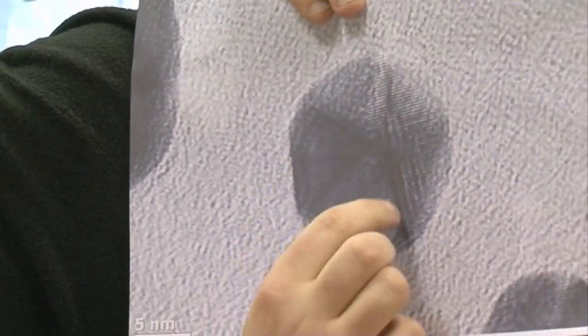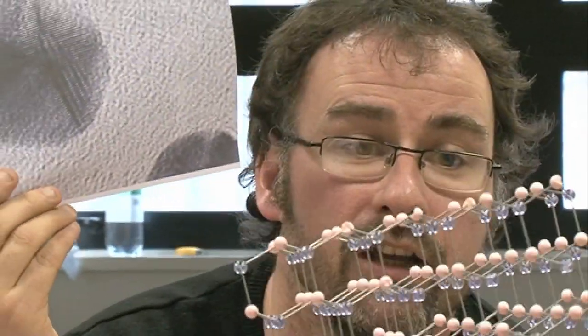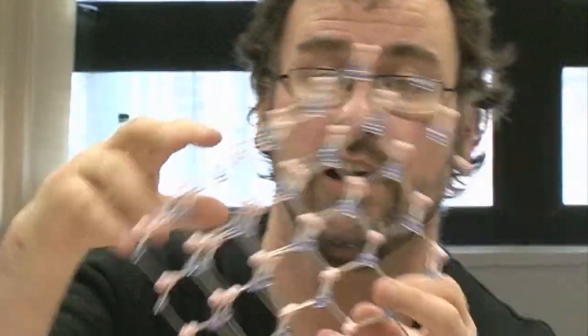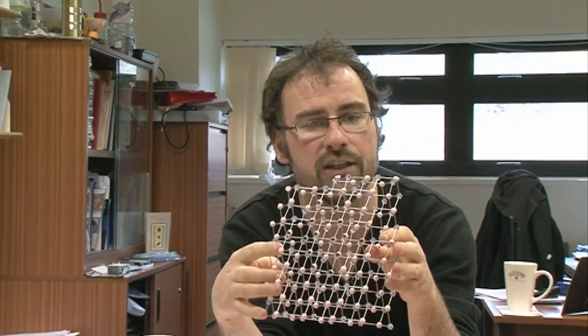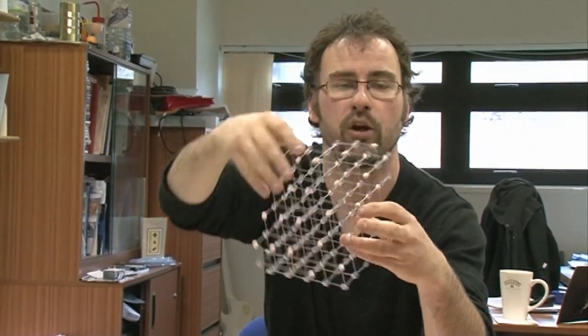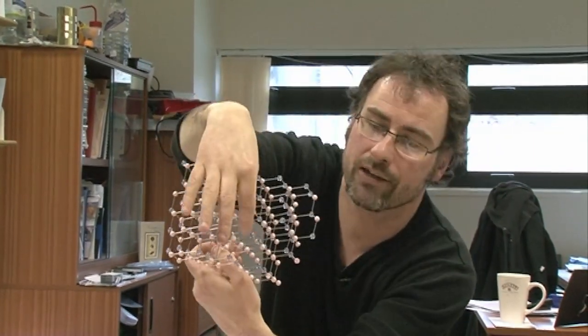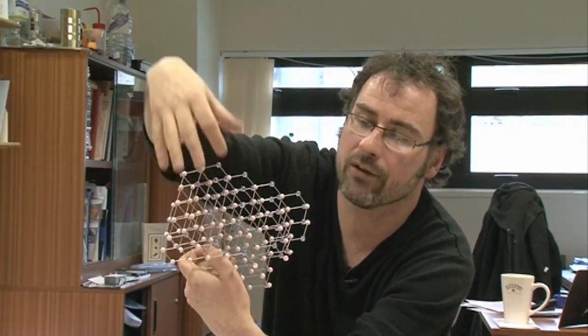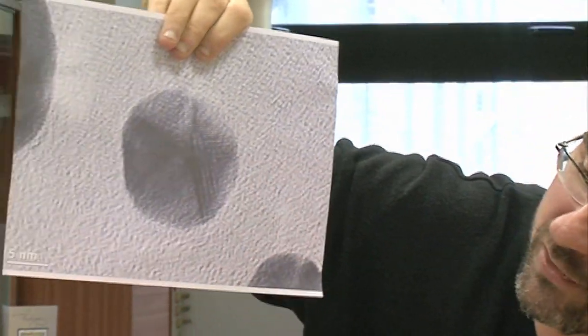You can sort of see these ridges, these edges, and those arise because when you form these particles, they grow out to a certain size and they have certain faces. It's not quite the same crystal structure, but it doesn't really matter, as gold has. And you have different faces, and those faces will have different reactivities, because if we look at different atoms on these faces, sometimes they're bonded to three atoms below, sometimes to two atoms below. That leaves what are called dangling bonds sticking out, and those dangling bonds affect the reactivity, affect how the crystal grows. Some crystal faces will grow faster than others, and we end up with these facets. When you grow crystals, you can grow them out to very large structures.